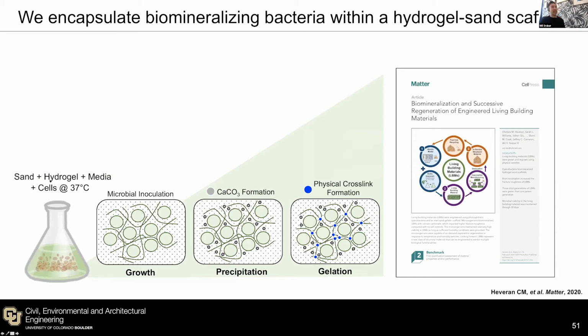And how we did this was we took sand, hydrogel, the media that the organisms need and the cells, and we mixed it all together. And inside, as these organisms were growing, they were precipitating these biominerals that were helping to cement the sand particles together. There was also this hydrogel that was kind of helping to keep all of the moisture inside of the material, especially once we cooled the material from an elevated temperature. Cells generally like to grow a lot faster the higher the temperature. But once we cooled the material, we formed kind of a jello around the cells that had all of the minerals inside of it and the sand.